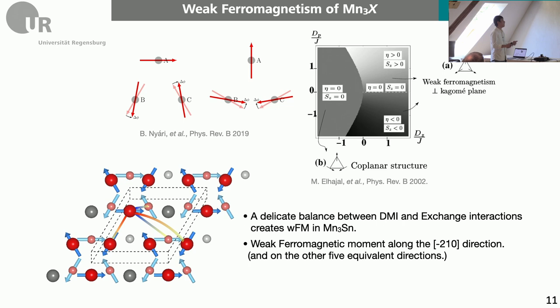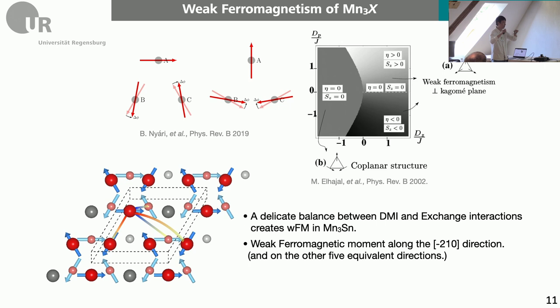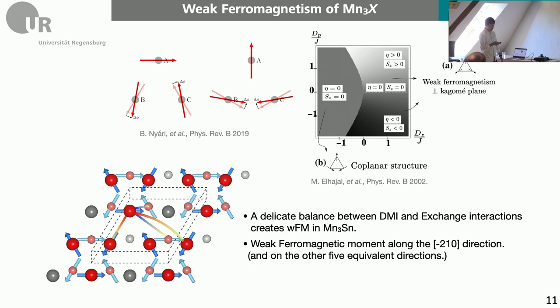In our case, the spins lie only on the basal plane — there is no component along the C direction. Because these two spins are canting slightly off from their easy axis, this slight tilting gives you a small net magnetic moment even though the system is antiferromagnetically ordered. The net magnetic moment is extremely small compared to usual ferromagnetic materials. In the case of manganese-3-tin, it has approximately a thousand times smaller magnetization compared to permalloy.